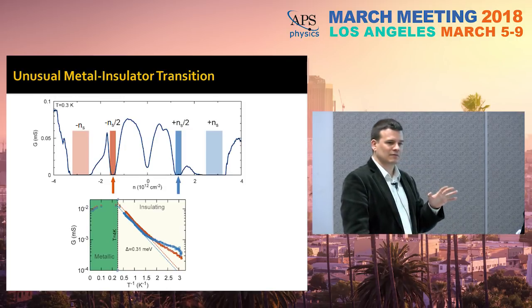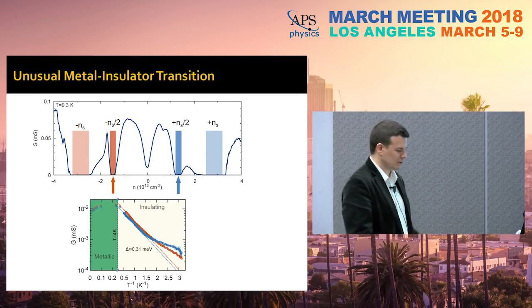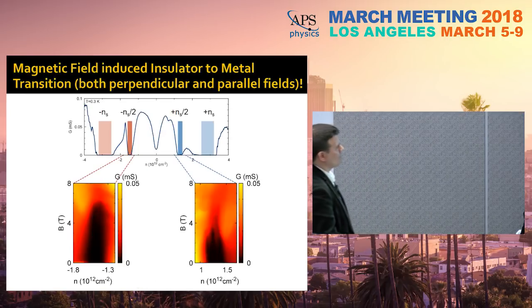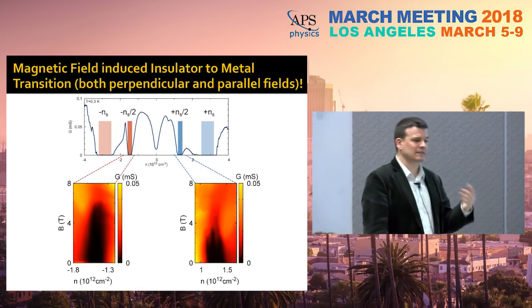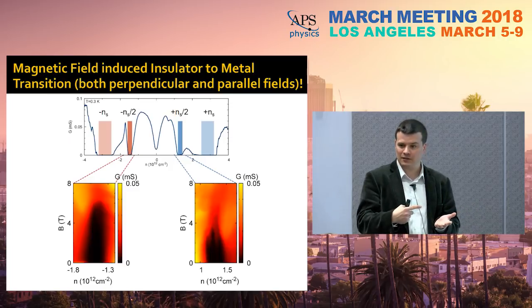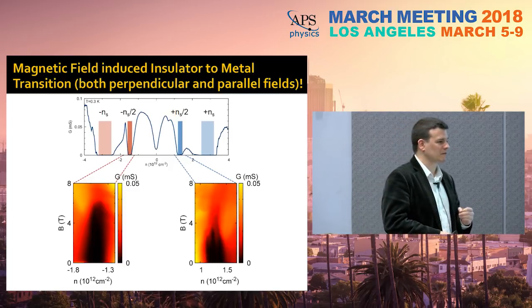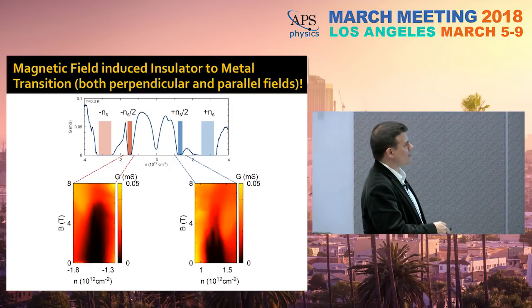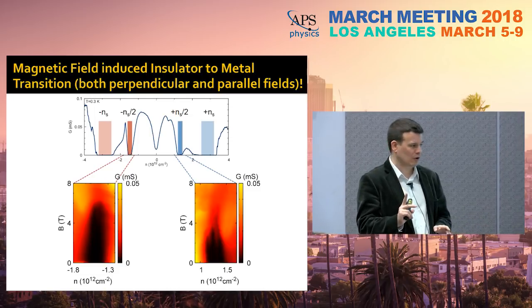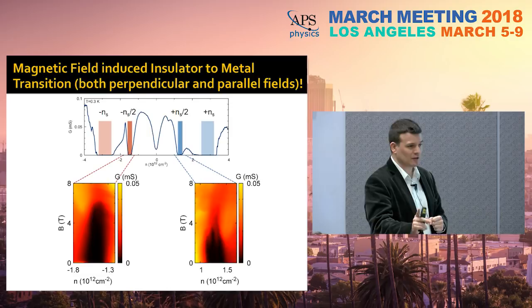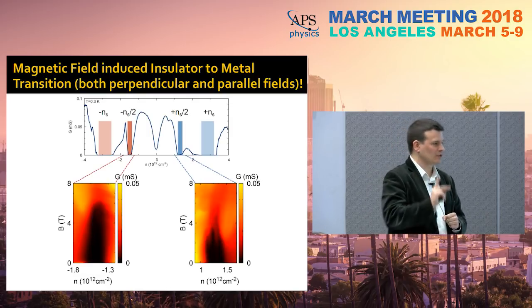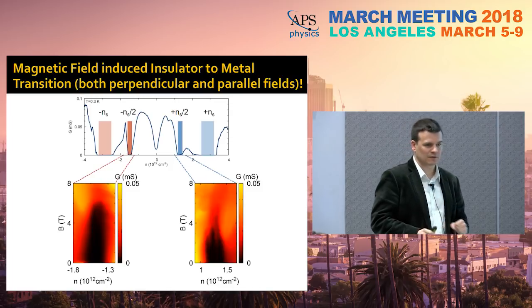But the most dramatic difference with respect to any other insulating state we had seen before was the following. In a magnetic field, and it doesn't matter if it's perpendicular or parallel to the graphene system, but it's most surprising that it's in a perpendicular field, the system goes from an insulator to a metal. Everything in graphene, when you apply a magnetic field, goes from metal to insulator or from insulator to more insulator. Okay? Nothing goes from insulator to metal when you apply a perpendicular magnetic field. Okay? So this was really very surprising.